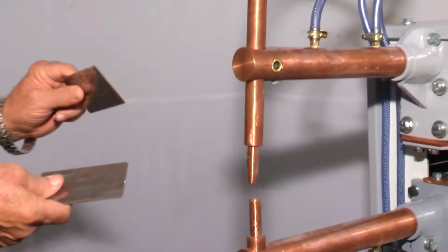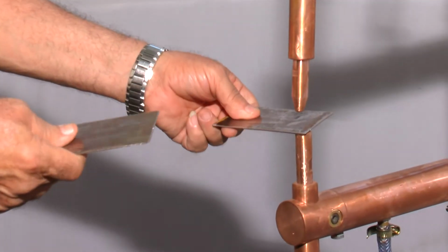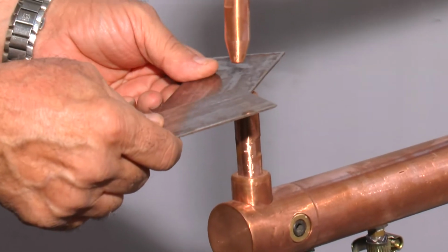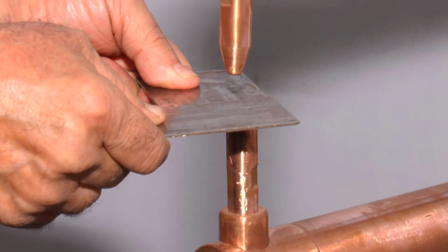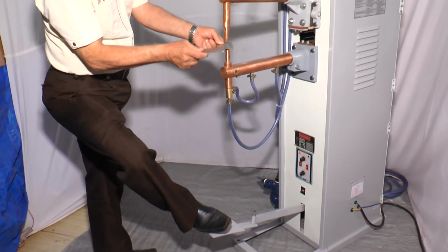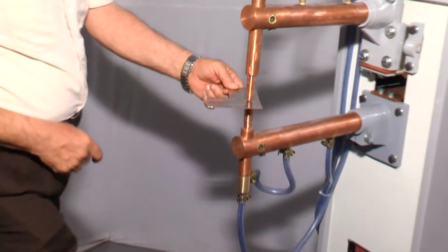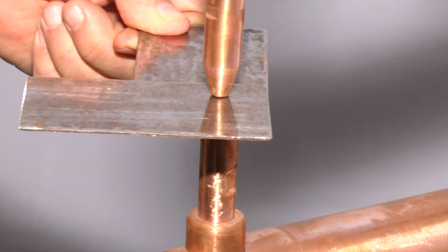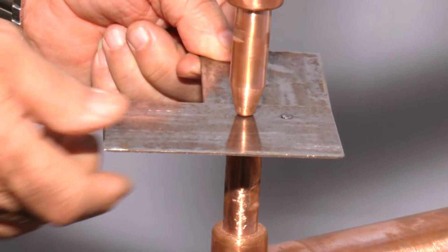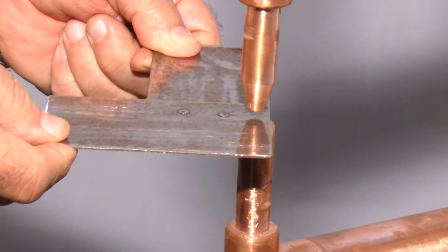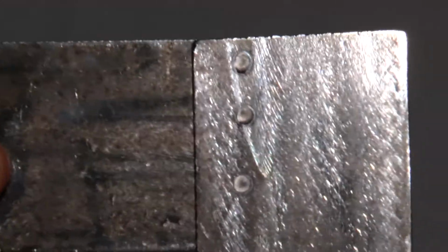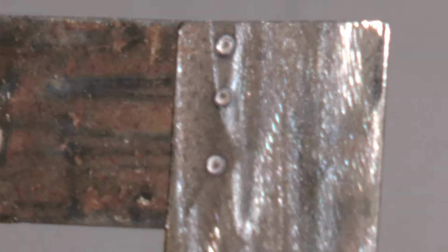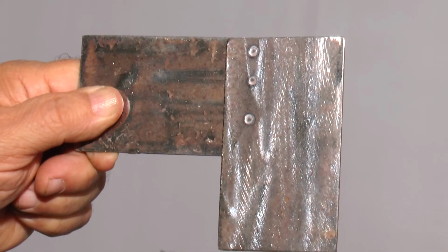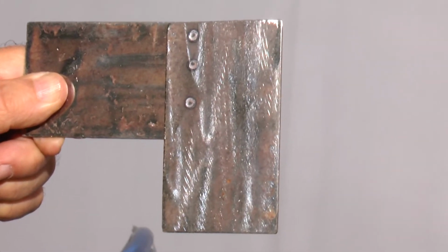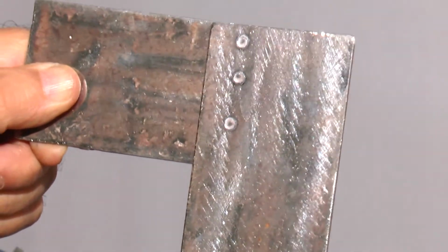Now we will show you the welding of two sheets which are thicker. Keep both the sheets between the two electrodes and then press this pedal fully. You shall observe the welding will take place and the current cutoff will be automatic. Just see. See, we have welded 3 spots. The weld strength is good. In case you don't get a good weld strength, you can increase the weld current and the weld timing, whereas the pressure is pre-adjusted at our works.